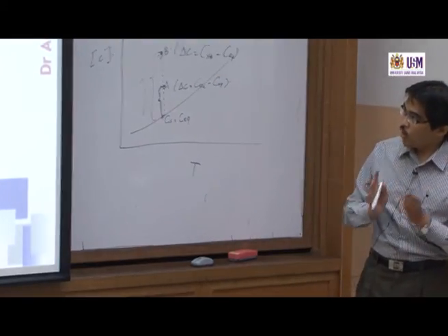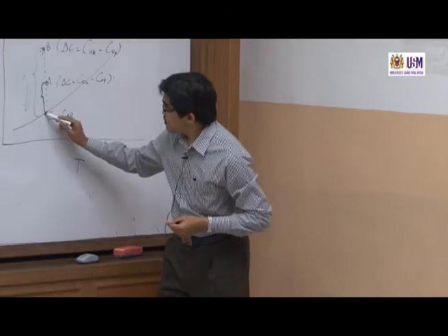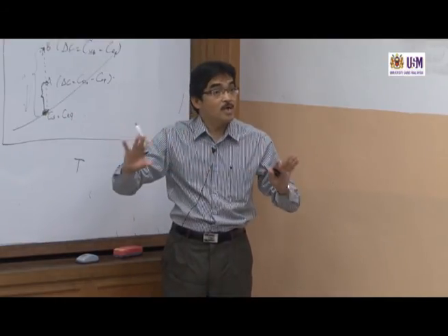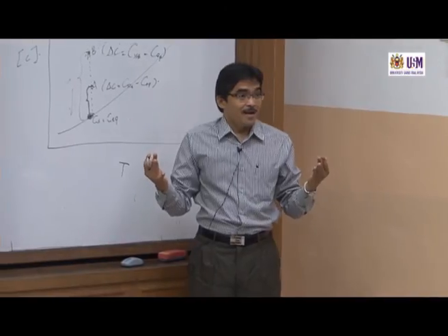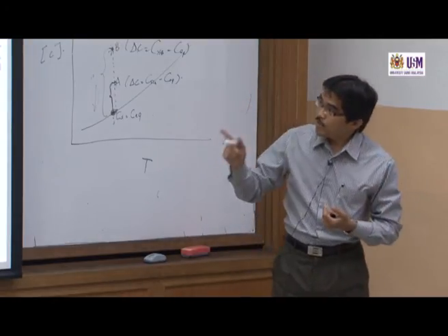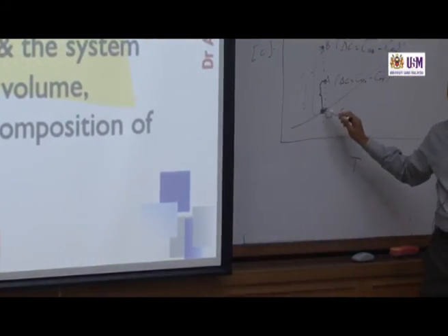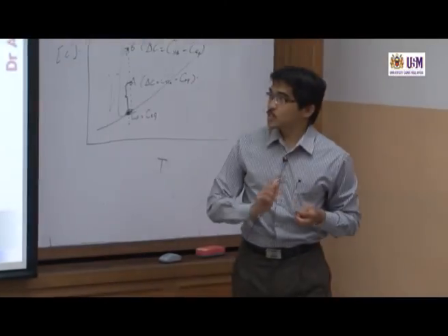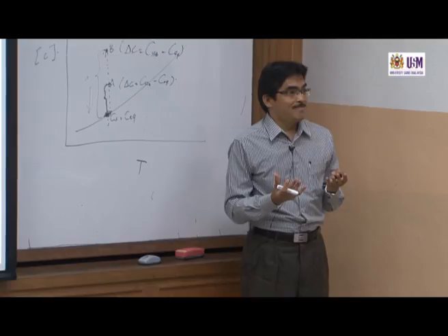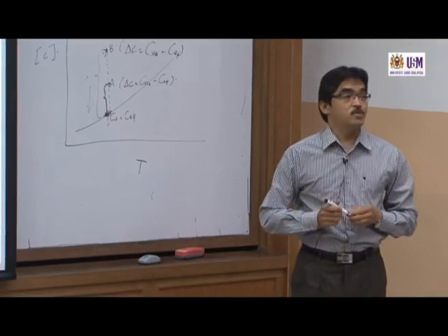Growth continues until all of the available supersaturation has been depleted. When it reaches this point, the available supersaturation is depleted. Habis dah. At this point, it's already equilibrium. Below this point, it becomes undersaturated already. That is what it means: all of the available supersaturation has been depleted, down to this point. And the system approaches an equilibrium in phase volume. When it reaches this point, no more crystal can be formed. Maximum already. Which depends on the temperature and composition of the system.